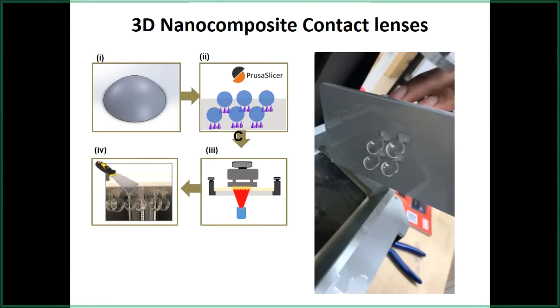Actually, our devices have not interacted with the body as yet, because they are not approved clinically. But the ones with nanoparticles, for example, these nanoparticles have been reported to be antibacterial at the same time. There are other groups making nanocomposite contact lenses for antibacterial properties as well. And if the nanoparticles are not on the surface, but trapped inside the gel media, then there is very little chance of them leaking out. So the toxicity issue would be very minimal, I think.